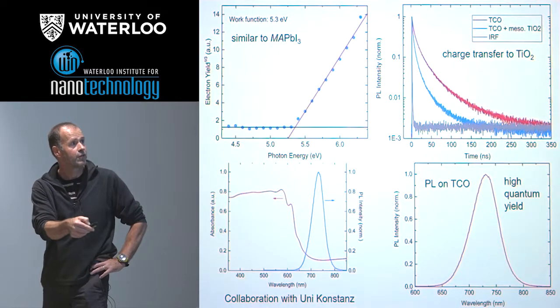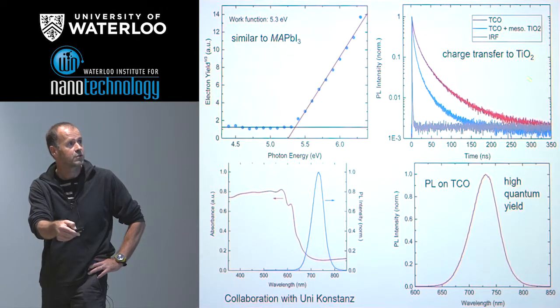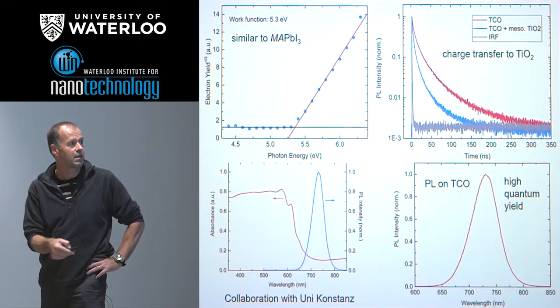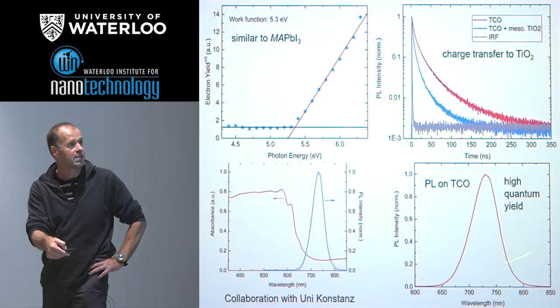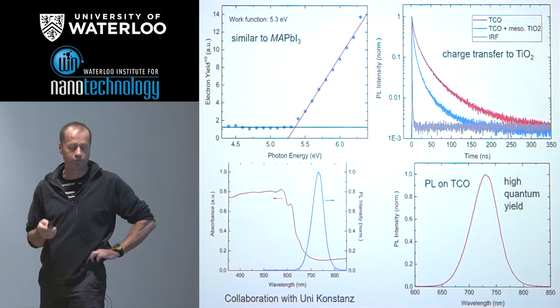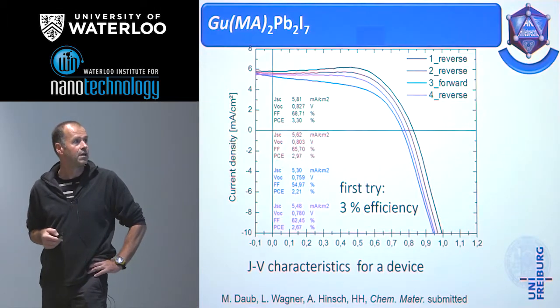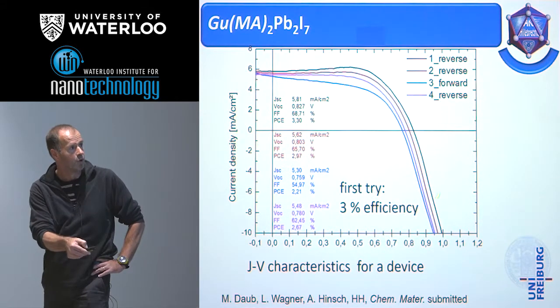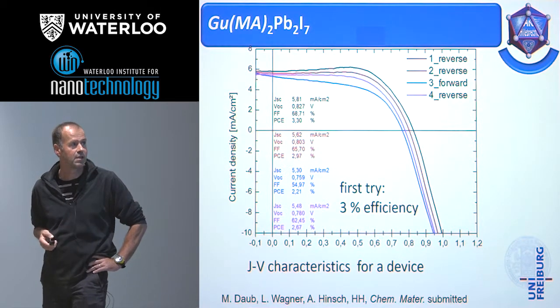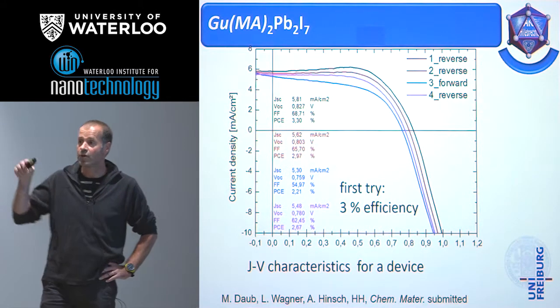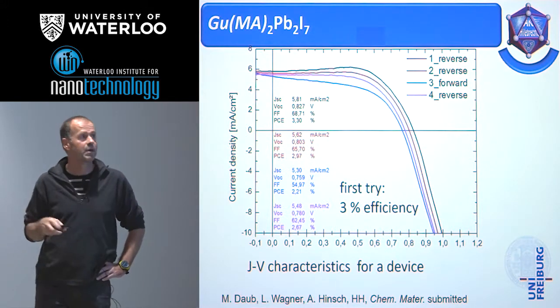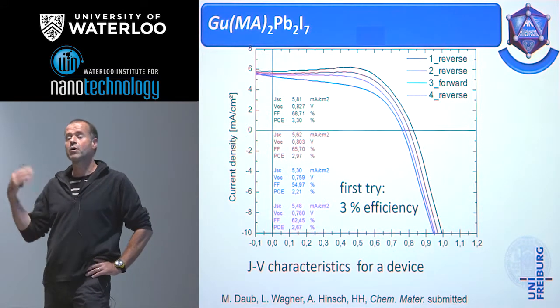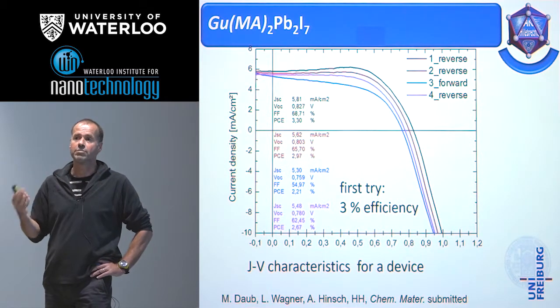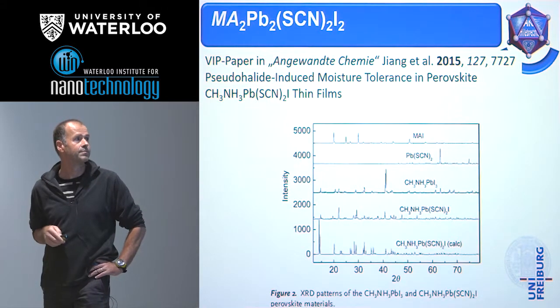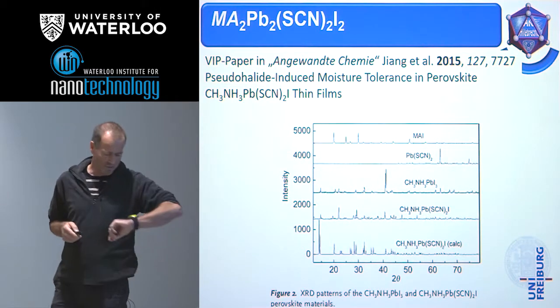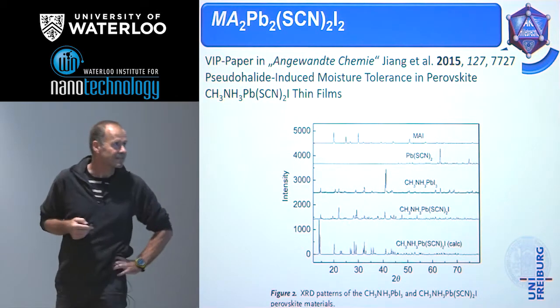We have measured the work function, we have measured the charge transfer to the mesoporous titanium dioxide layer, we have measured the optical properties, could show that we have an excellent quantum yield for the photoluminescence, and we had indeed a device that works. The first try was about 3% efficiency, and the important point, it really works with only our dye, because that's not always clear if you have the combination of different cations, which compound is really the active compound. Another example, I know that I should come to an end, but I will come.